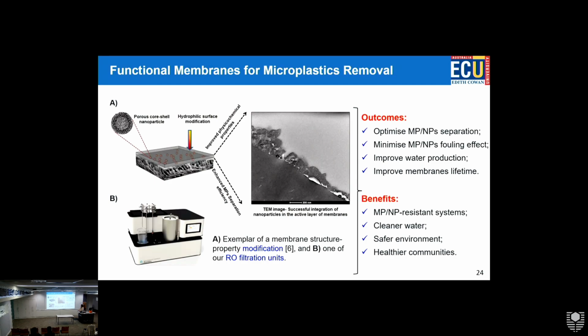In short, what we do is improve the surface properties of the membranes by integrating nanomaterials into the structure. For example, you see a TEM image here. This is the thin layer that I was talking about. This is around 200 nanometers. These are the same particles that have been integrated into the surface. This is from my PhD, a very long time ago, but I just wanted to show how these are integrated into the membrane.